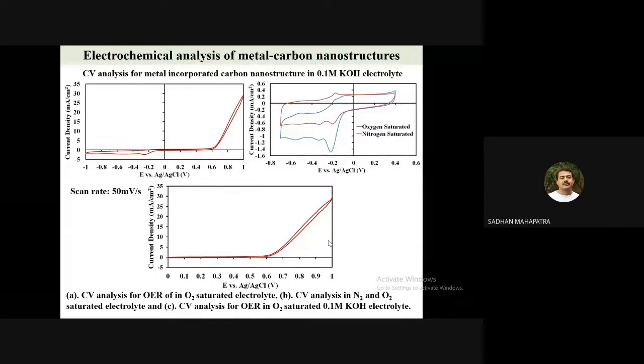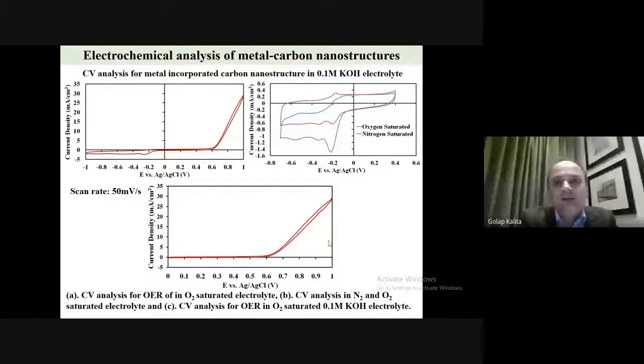So this is the electrochemical analysis of the metal carbon nanostructures. Again, we did this for a wide potential range. This is all still in silver chloride reference electrode. So this is OER going on. So here is your ORR activity. If we see only the ORR, this is for oxygen saturation in the solution. If we put oxygen gas, you can have much better ORR activity. And this is only the OER.